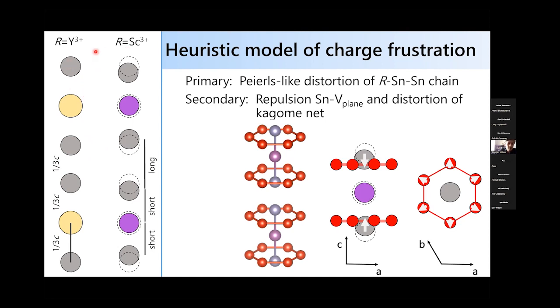So then what happens is if you replace yttrium with scandium, you put a much smaller atom in there, and that activates an instability, and it allows these tin atoms that were displaced to move in closer to the scandium site. So you can end up with a modulation of, let's call them trimer units, where you have a modulation along this chain of short and long bonds. And so you end up with a decomposition of this equally spaced chain into these maybe trimer units that can move together. If I think about this trimer unit along the c-axis and go one coordination level out, these are the vanadium ions. When these tin atoms try to move into the vanadium plane, they displace the vanadium ions out, and there's some steric penalty associated with that.